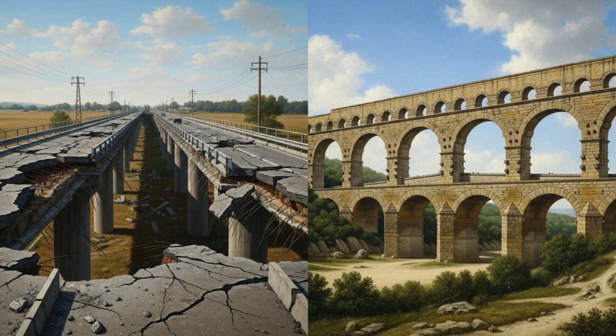When cracks form, these lime clasts get exposed to water. They dissolve, releasing calcium ions that precipitate as calcium carbonate, sealing the crack from the inside. It's not just self-healing. It's preloaded with healing agents, distributed throughout the structure. Waiting. The Romans engineered redundant self-repair mechanisms. Without knowing chemistry, without microscopes. They did it through trial, error, and genius observation.